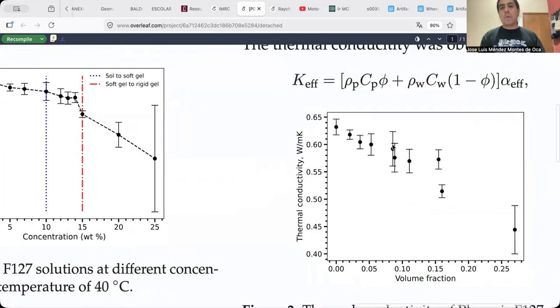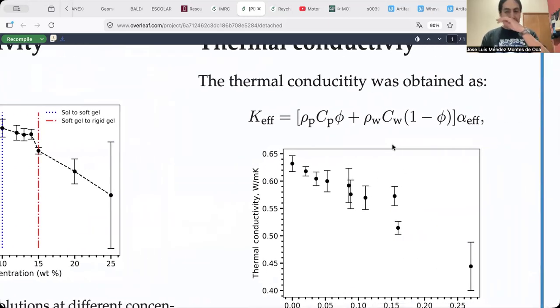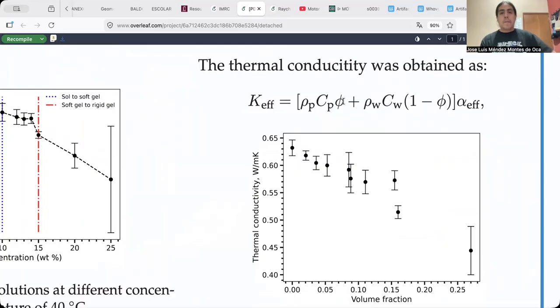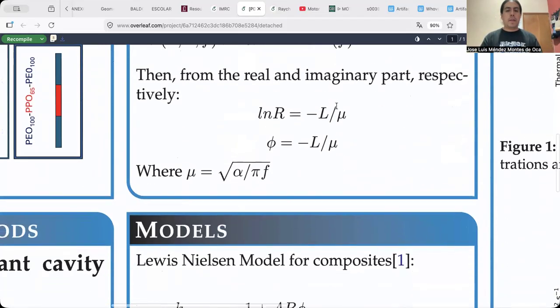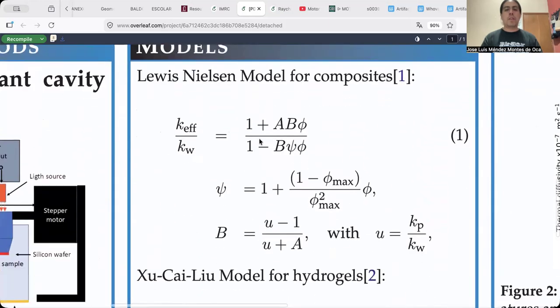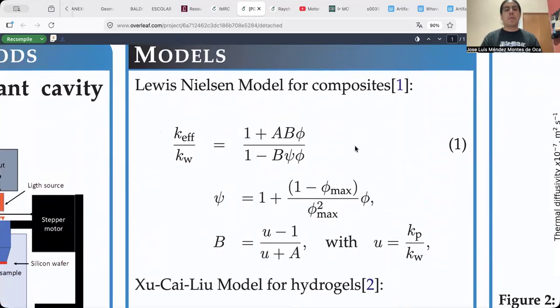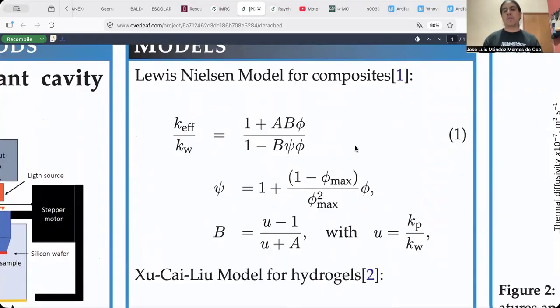Well, once the thermal diffusivity was obtained, the thermal conductivity of the samples was calculated by its definition as the product of the thermal diffusivity, the density, and the heat capacity. But in this case, the law of mixtures was used in terms of the volume fraction phi, defined as the volume of the polymer with respect to the whole volume of the system. And well, the thermal conductivity can be used to analyze our data with effective thermal models, which are usually written in terms of the thermal conductivity, as the thermal conductivity is an intrinsic property of the materials.